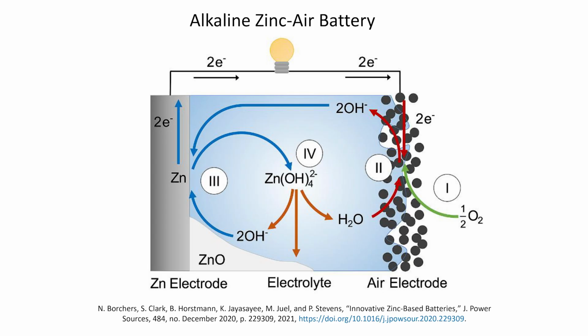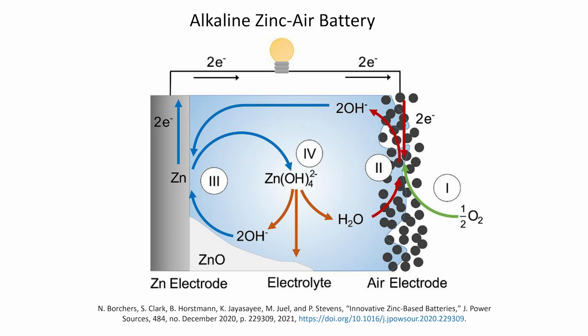Let's start on the air electrode side. First and foremost, if we're using air from the surroundings, we need a way to get it into the battery. And so our air electrode is usually a porous structure that is coated with an oxygen reduction catalyst, in many cases manganese dioxide, that allows the oxygen to come into the battery and create an interface between our catalyst and our electrolyte. Now, the electrolyte is the part of the battery that's responsible for moving charge between the different electrodes. So our electrolyte is going to partially fill that porous structure where our oxygen is coming in, and transport hydroxide ions from the positive electrode through the separator to our zinc electrode, which is basically a lump of zinc paste.